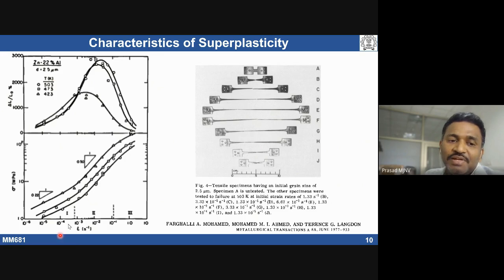Similarly, if you look here, for the same grain size, the effect of temperature: with increasing temperature, typically stress value is going to come down. So this is low temperature, intermediate temperature, high temperature. At a given strain rate, higher the temperature, lower the stress.